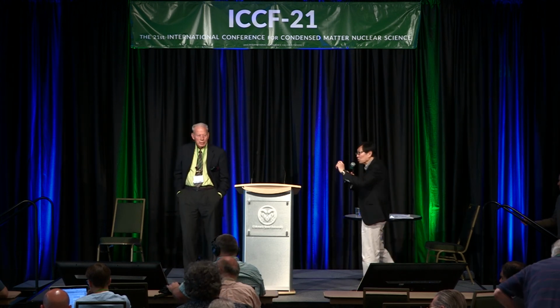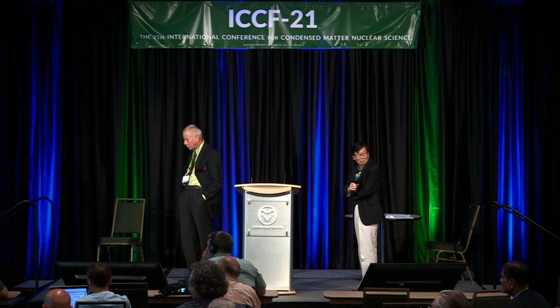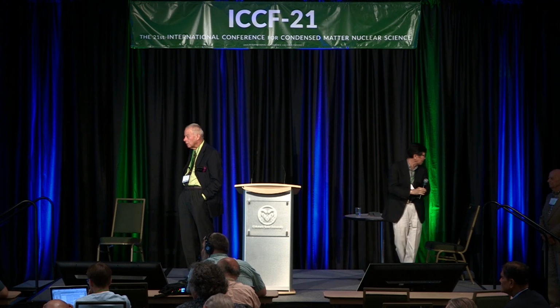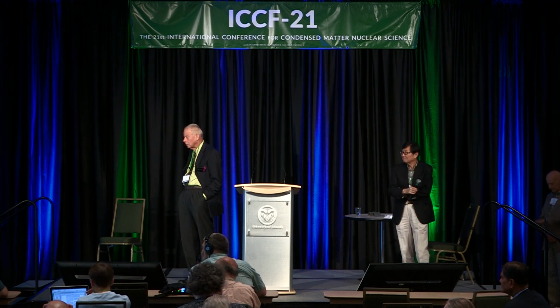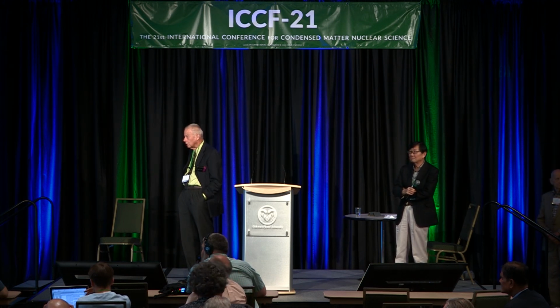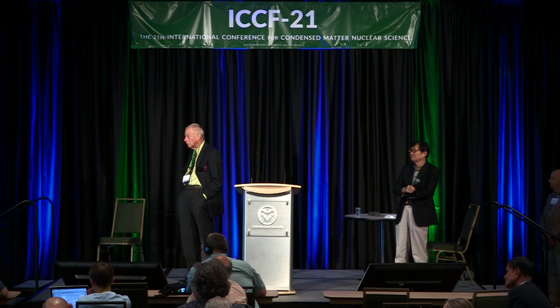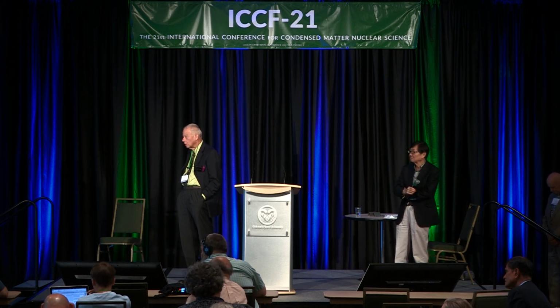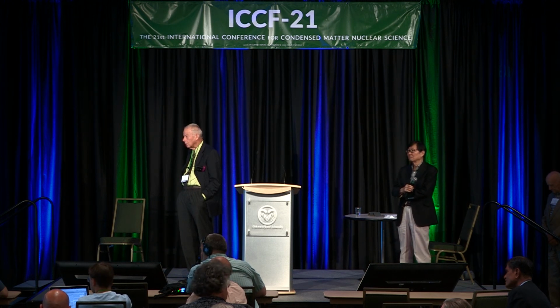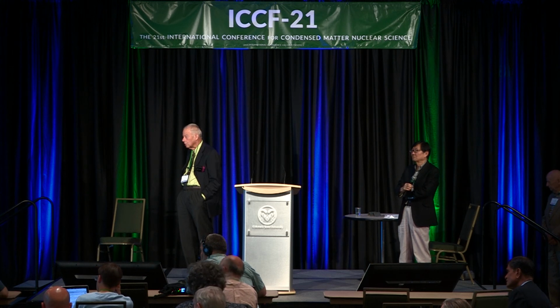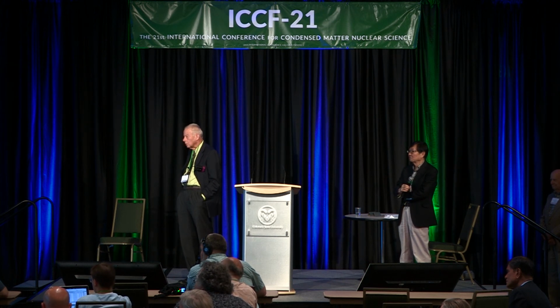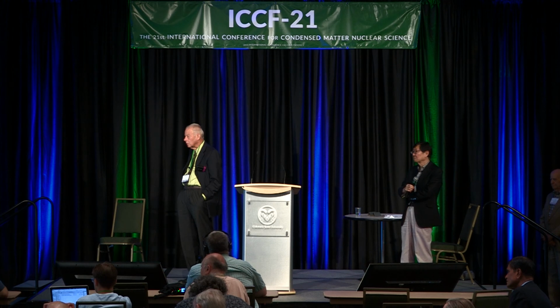Okay. I hate to pour cold water on this, but it's very important that we look at the palladium-boron system. I think you've essentially shown us a possible path. But what I have to say is that I have tried that path myself, independent of samples that you supplied. These were supplied from other sources, and I have failed to see not only the ability to load, but any excess energy. So there is another variable obviously operating. And I would suggest that it's really necessary to start looking at this in a more objective way, using modern equipment and information that we have available now that you did not have available at the time you did those other experiments, to try to figure out exactly what's going on, because there's something else besides what we think is going on.